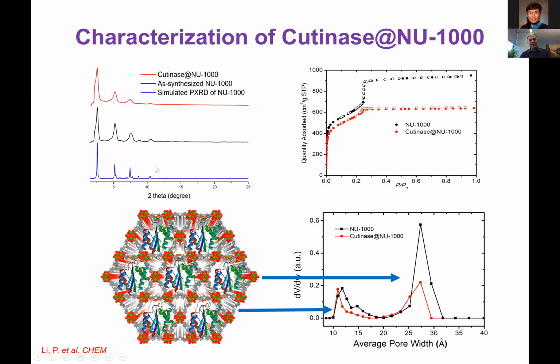Here we do PXRD, and that means our structure is still intact. So how do we know that our enzyme is actually inside the hexagons and not the triangles? We do nitrogen isotherms. For the people who are not familiar with nitrogen isotherms, we measure the uptake of nitrogen at 77 K with respect to pressure. Here, the black curve of this particular isotherm is before we put the enzyme inside our material.